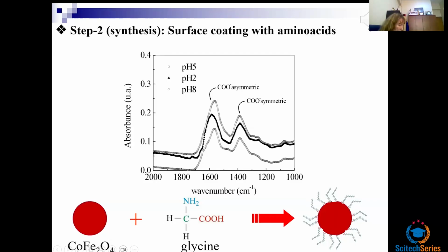So here is one of the amino acids, the glycine. So the cobalt ferrite nanoparticles are coated with glycine, and actually the best pH to perform this coating was exactly pH 5, which gives the best surface coating of the nanoparticles.